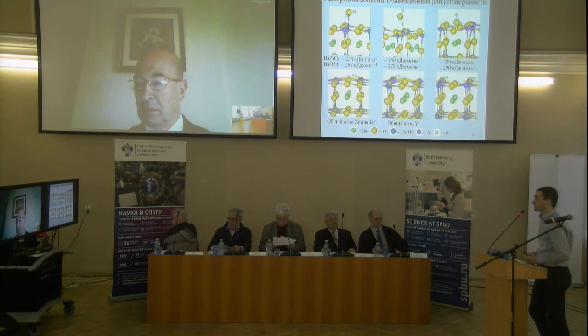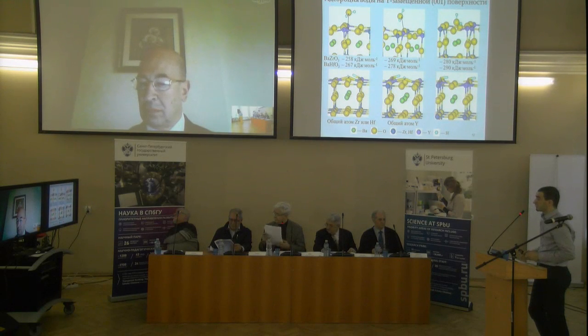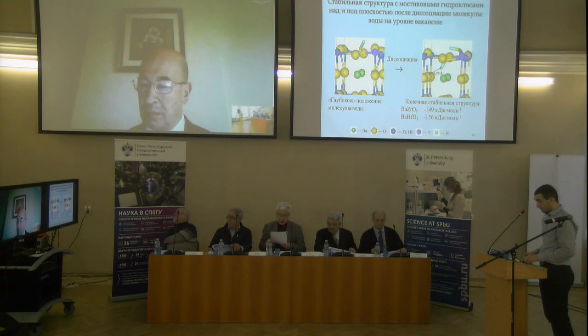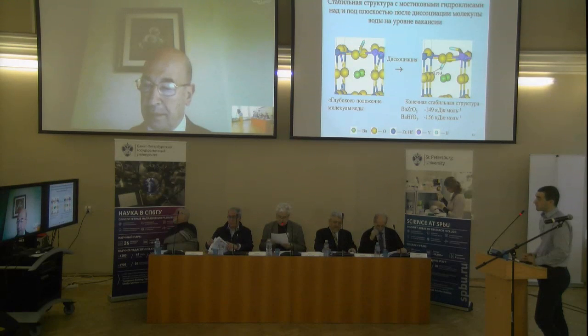Simulation of mixed adsorption is possible only when using the expanded cell. In this case, one of the water molecules per unit cell retains the molecular form, and the other dissociates. Energy adsorption of water suggests that the interaction of water with the surface is a rather exothermic process.